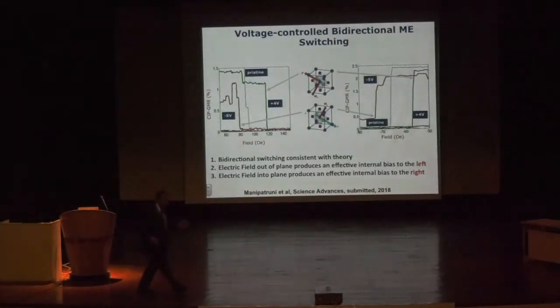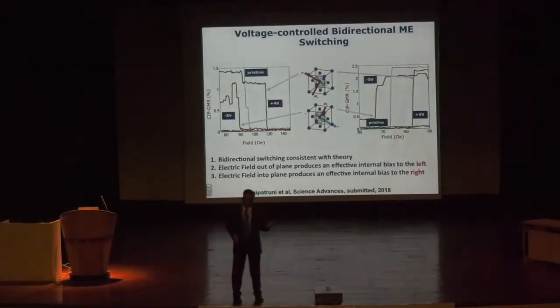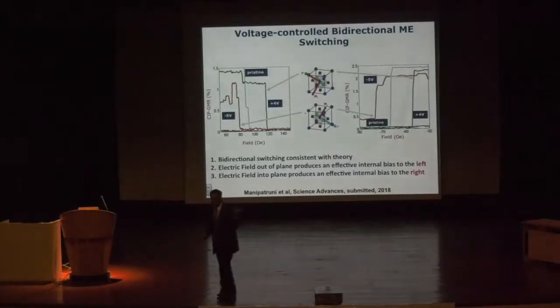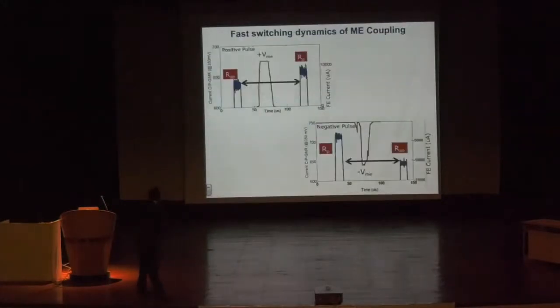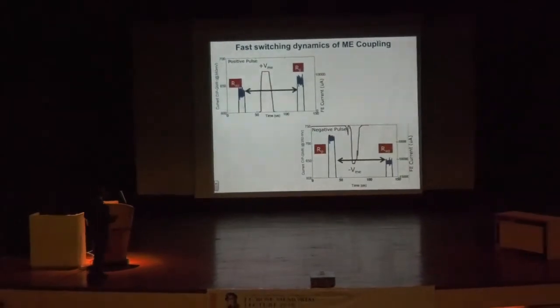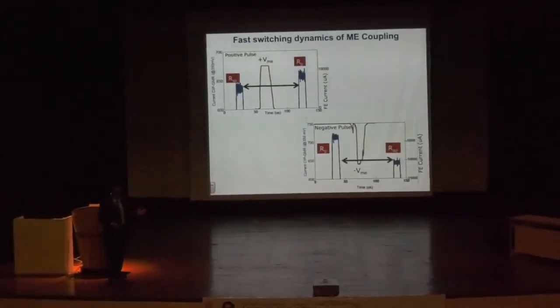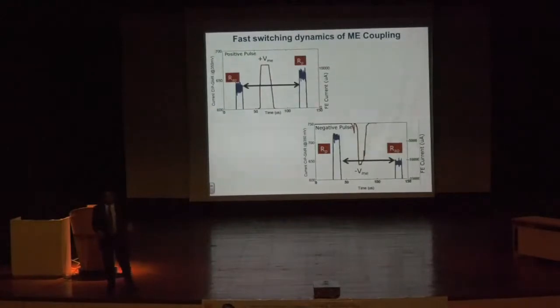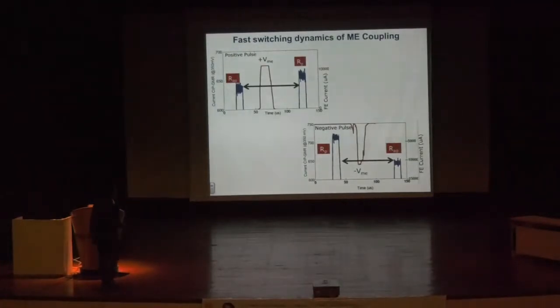Okay. So by now, I hope you have gotten this one message which says, hey, at 8 volts, I can switch my magnetization direction by 180 degrees by applying an electric field. Okay? So that's a first level summary. We did some faster measurements. This is just data showing you that we can do it at a few microseconds, maybe 10, 20 microseconds. And ideally, you can go at the acoustic phonon mode. The switching speed for ferroelectrics is controlled by the acoustic phonon mode, typically the velocity of sound. So we think we can go at maybe nanosecond or faster, no problems.